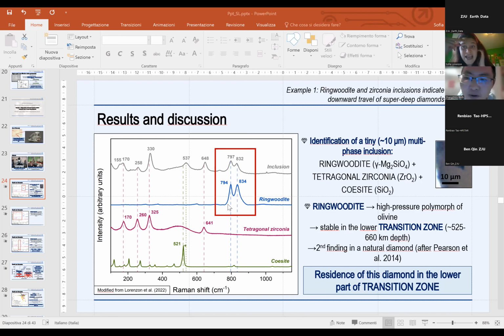But in our case, we think that for this very high Raman shift, we cannot have a right result, because we cannot know the anisotropic effects. This pressure can also be anisotropic, and we cannot know how the anisotropic properties change the Raman shift of this spectrum. So we didn't calculate this, because we cannot consider this result as a good result for our study.